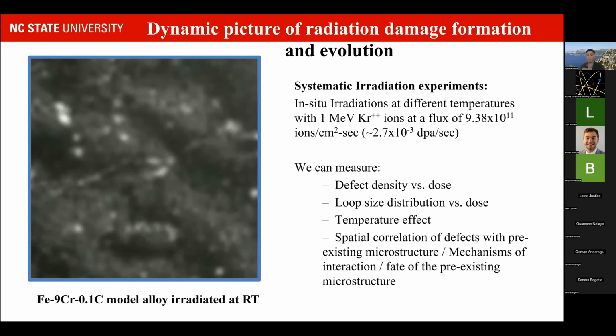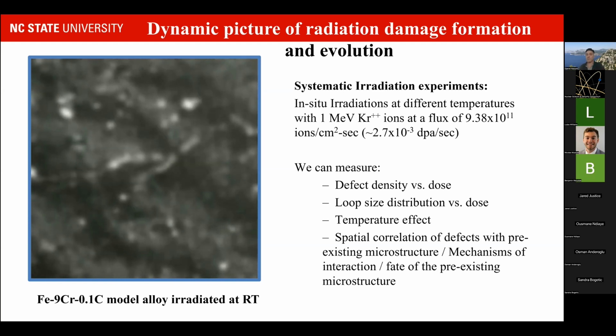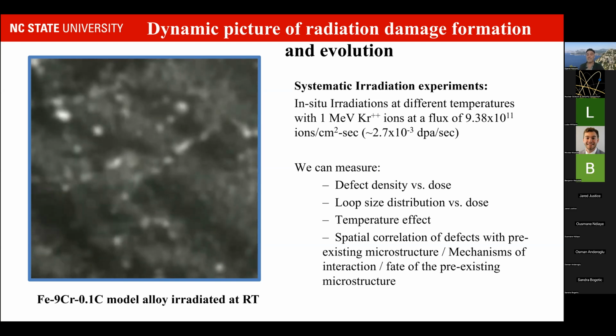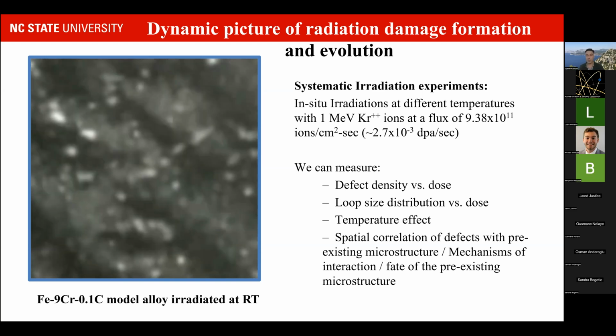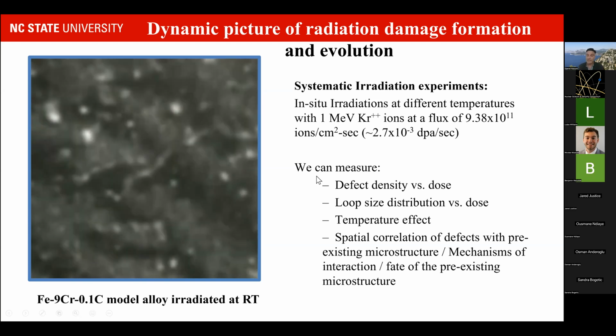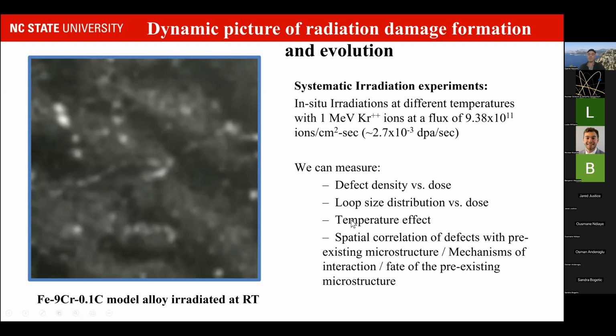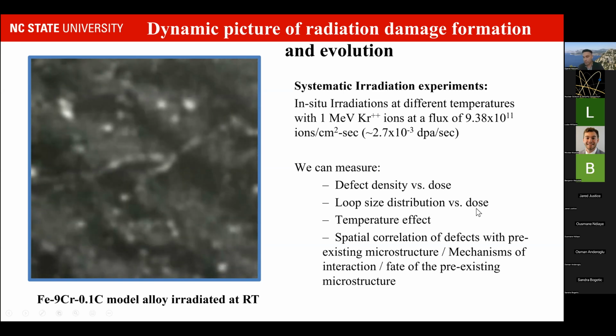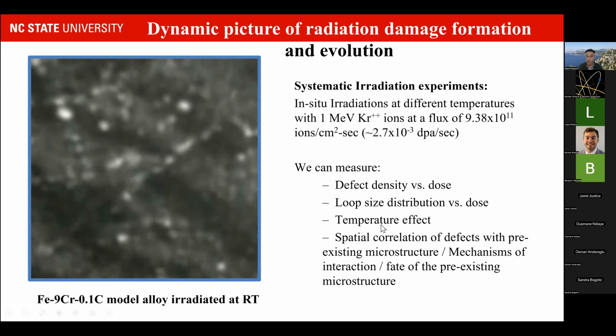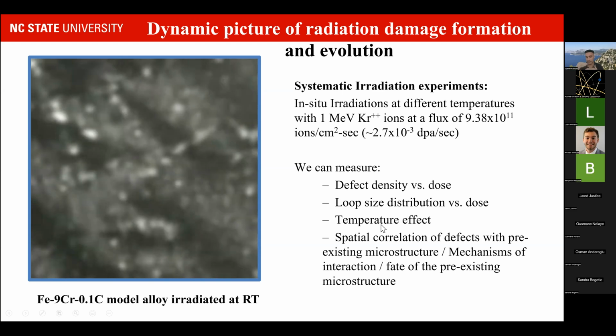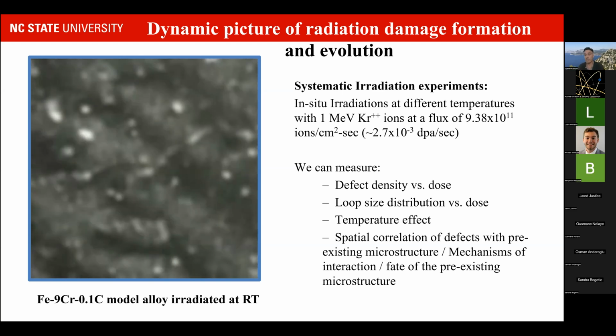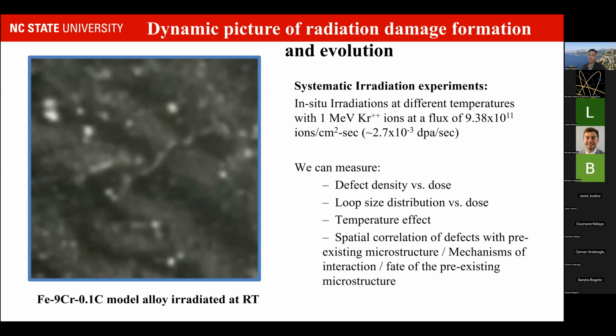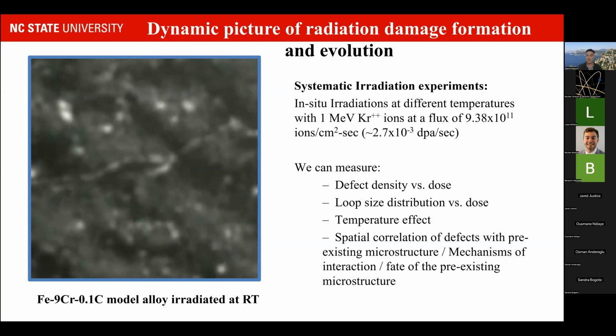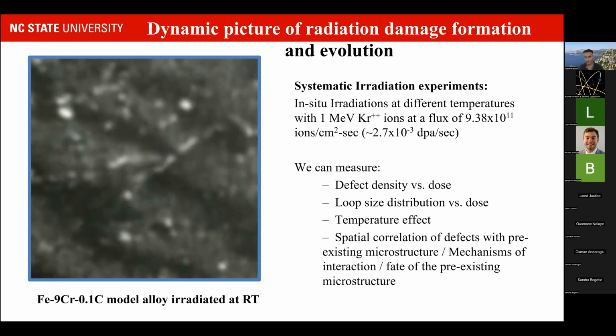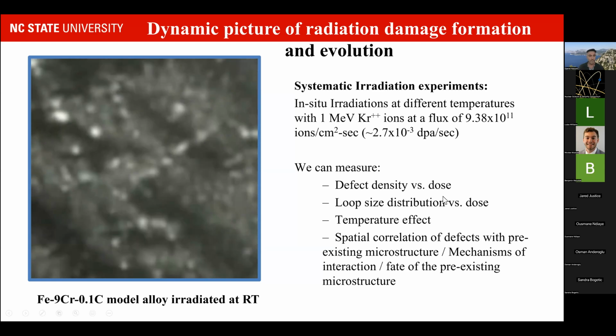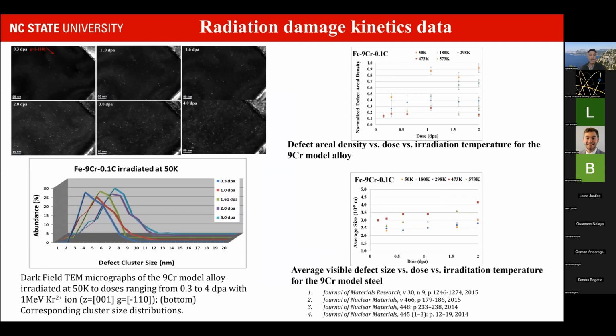But we can also do systematic experiments that will allow us to determine kinetics information, which I was mentioning earlier. I'm talking about defect density versus dose, loop size distribution versus dose, and the temperature effect when we systematically do the same experiment at different temperatures. And importantly, we can also see the spatial correlation of defects with the pre-existing microstructure. That is something I'm going to illustrate.